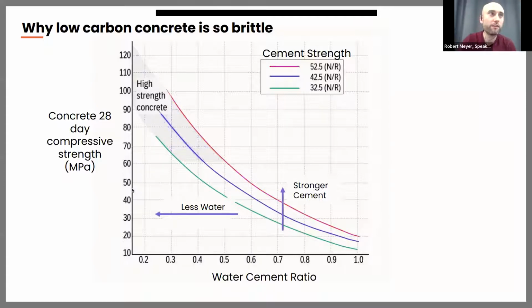If concrete's most important property is strength, how can I actually modify the strength of concrete? There are basically 2 levels. One is the most straightforward one: using better cement. If I use stronger cement, I get stronger concrete, which is depicted here by these 3 different colored lines. The green line depicts weak cement, the blue one is medium strong cement, and the red one is strong cement. If I go in that direction and take stronger cement, as you can see on the y-axis here, I get stronger concrete, straightforward.